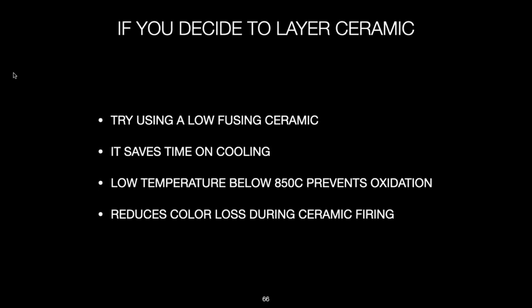So if you do decide to layer, you need to use a low fusing ceramic better than a high fusing one. It saves on the cooling time a lot. I like to go below 850 for glazing and everything because if you have some coloration, it might burn it away. So you could have an A3 and you end up with an A2 on some full contour crowns. But if you're layering, the facial, the occlusal table will get lighter. And that's because the pigments inside close to the surface are being oxidized away. That's my conclusion. I've seen it happen too many times.